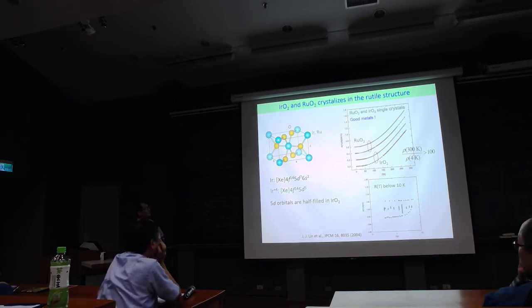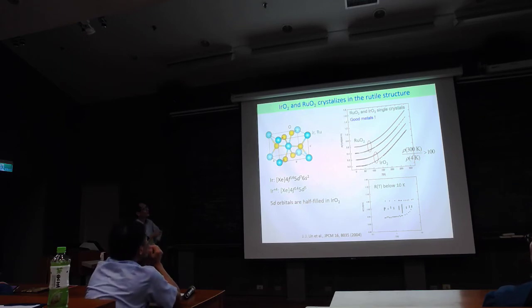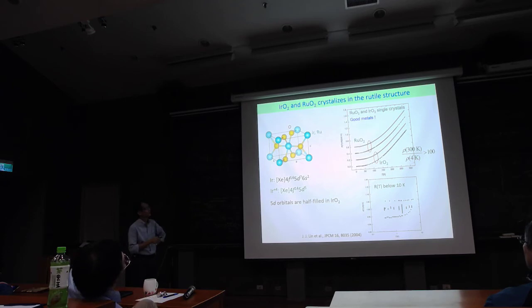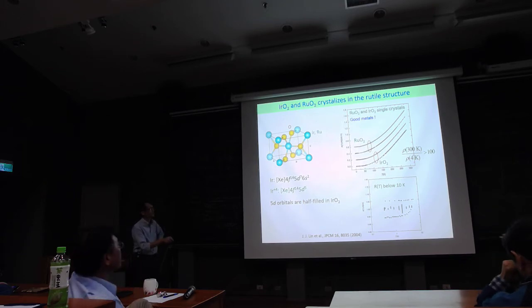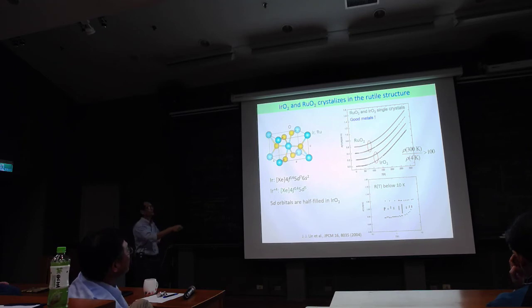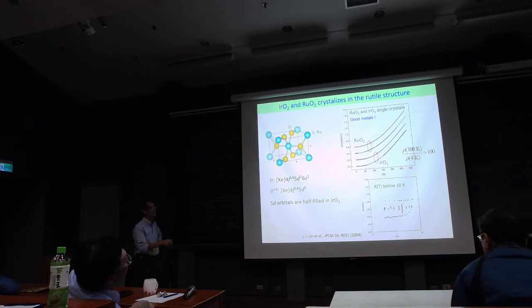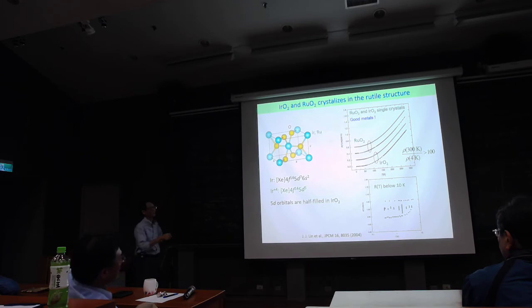We have worked on these two oxides for many years. It is interesting that they are oxides, but they are metals, very good metals. Not only from our measurements, energy band calculations also confirm that they are metals. So, for example, here are two ruthenium dioxide single crystals and two iridium dioxide single crystals. From room temperature down to low temperatures, you can see that as the temperature decreases, the lattice vibrations become weaker and weaker, and then resistivity decreases.